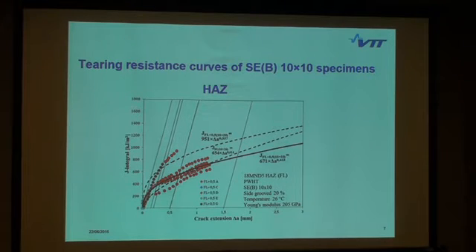And in this case, there seems once again to be a situation related to the crack location, because there's this one heat affected zone curve that exactly follows for 10 times 10 specimens, and the 10 times 20 specimen follows the same curve, and possibly they are at the same location of the fusion line, and these data are closer to the fusion line. There might also be some effects related to constraint, but they cannot be concluded yet from here, but the location of the crack seems to be the most important factor affecting these differences in the results.